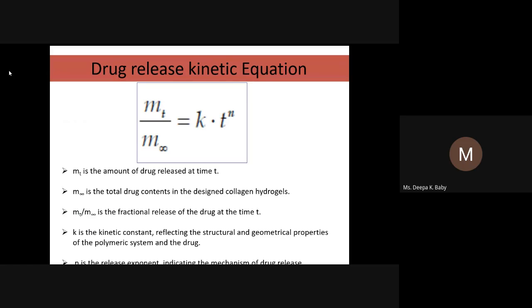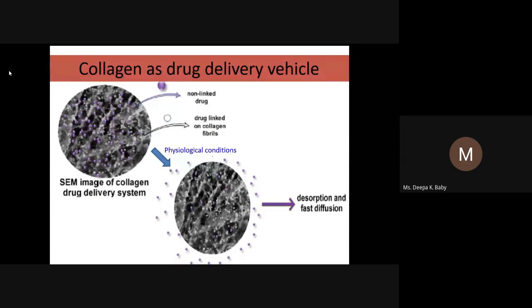Then if you are using hydrogel for drug release, you can use this equation for finding out the release of drug from the hydrogel, where Mt/M∞ = K·t^n, where Mt is the amount of drug released and M∞ is the total drug content in the hydrogel, and Mt/M∞ is known as the fractional release. K is the kinetic constant and n is the release exponent and depends upon the mechanism of drug release that we will see later. And this is the picture of the collagen, which is acting as a drug delivery.